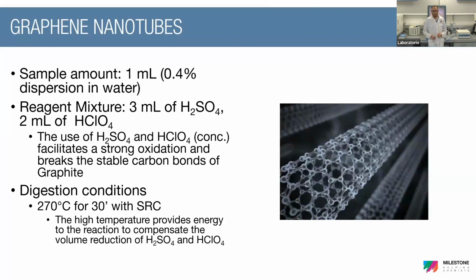And together with this, we digest the sample at very high temperature conditions using the UltraWAVE system, the single reaction chamber system, and I'm talking about 270 degrees. And this energy, together with the chemical mixture, helps to break the carbon bonds and then to have the dissolution of these samples into the liquid, into the acid. Another point that I want to focus on here is related to the volume of the acids. Notice that the amount of acids used is very small. We are talking about 3 ml of sulfuric and 2 ml of perchloric.